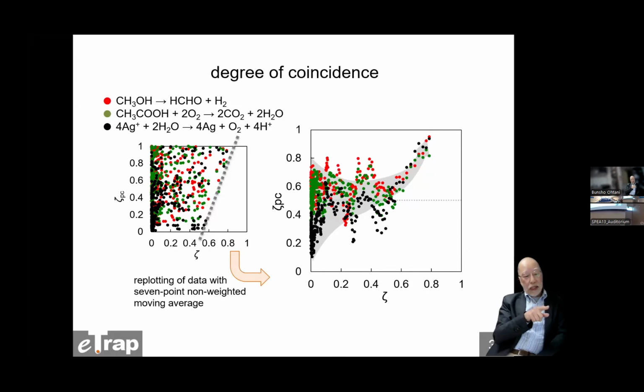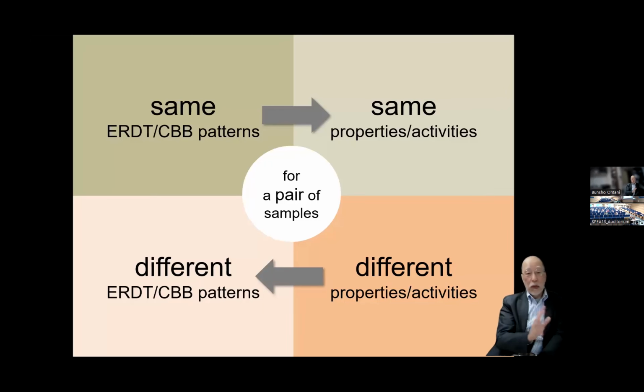And it is expected that if the zeta value is higher than 0.8, zeta PC value may become almost 1. So that means if the zeta value is higher than 0.8, they are almost identical, the same titanium oxide. So therefore, the photocatalytic activity must be almost the same. So this zeta value is a very good index for similarity or identicalness of titanium oxide photocatalyst.